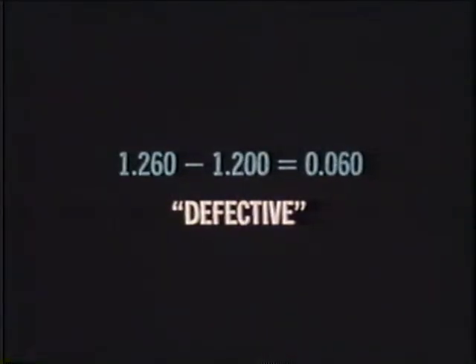Next, when using the hydrometer, carefully insert the probe into the cell so as not to damage the top of the plates. Check the specific gravity of each cell and note the highest and lowest cell reading. A variation of more than 50 points means the battery has lost capacity and should be replaced. If any cell reading was less than 1200, the battery must be charged until all cells are over 1200.